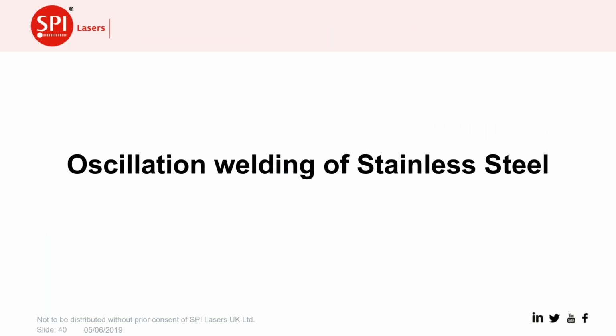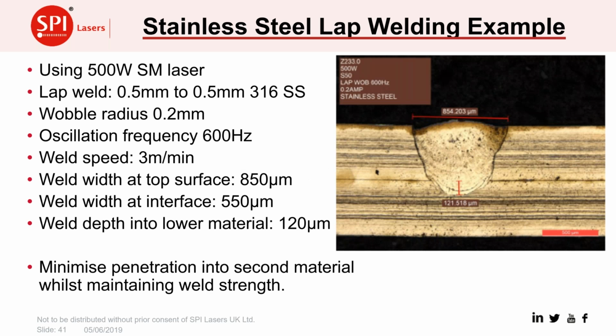And finally, just a couple of slides about welding stainless steel. Yes, we can weld stainless steel. Sometimes on the top surface, you do need shield gas to get a good quality top surface of stainless steel with oscillation welding. But here we were able to produce a good wide weld interface. Again, this is what's required here, but with minimum penetration into the second material to control the heat that went through to the bottom part. By setting up the parameters, you can produce a very wide weld interface with very little penetration into the second material. So you get the strength that you need.